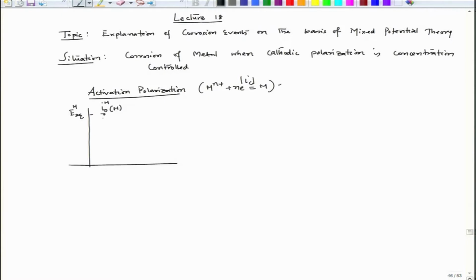Now, if this is the point, I can have activation polarization, which is decided by I 0. So, this equation, which is the Tafel equation, is the controlling factor. This axis is log I. So, the potential drops due to cathodic polarization. We are talking about cathodic polarization, and this line is nothing but the variation of I c.